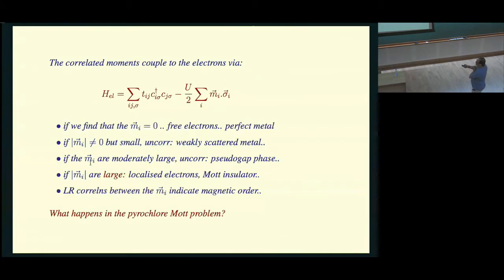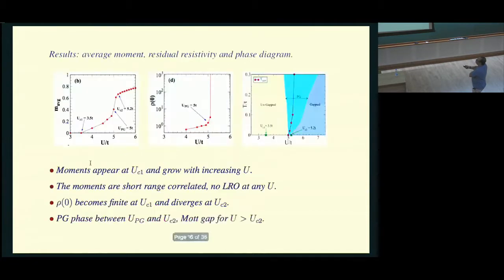So what is the consequence of this in the pyrochlore problem? In the pyrochlore lattice, if you go through this process, you discover that as you increase the strength of interaction in the model, beyond a critical value, whatever it may be, I call it UC1, you begin to see a weak increase in the value of the typical magnetic moment.